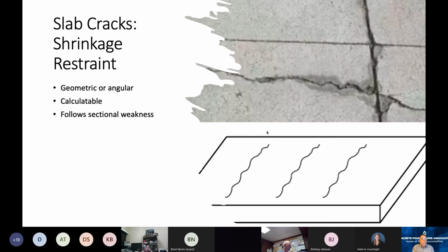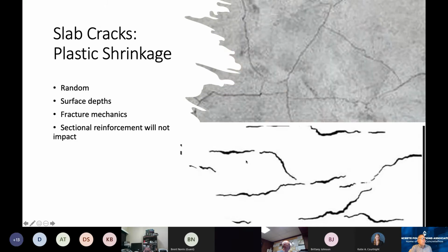Now, I can also use cracking to tell a contractor that they didn't meet tolerance on a slab. If I've got a shrinkage crack that misses the intended joint by a foot or more, I can begin to calculate the slab thickness and tell them that in this particular area of the slab, they probably had a bulge in their subbase, and instead of being a 4-inch slab, it's only 3.5, or maybe 3 1/4. Sometimes I've seen slabs get down to 2 3/4 inches, and there's where the crack occurs. So it's almost always going to follow sectional weakness. In fact, I think it is always going to follow sectional weakness.